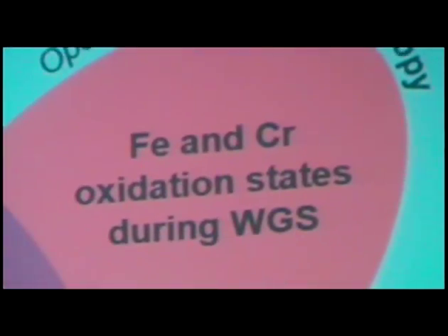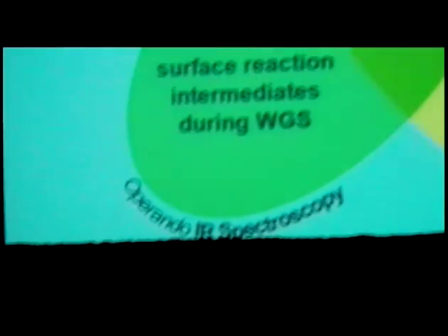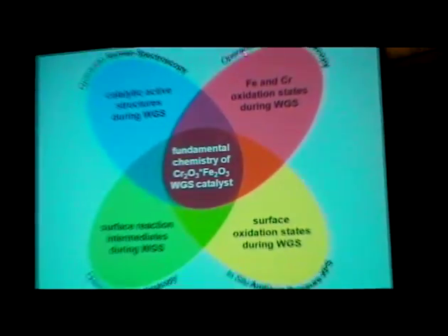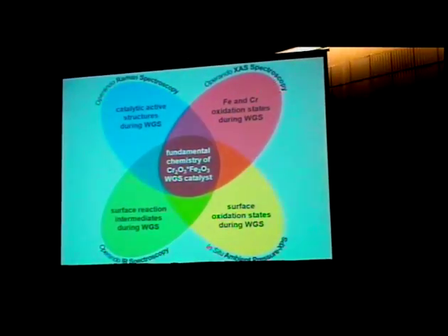So this is the strategy that we took to learn about the catalytic active structures during the water gas shift. We performed so-called operando Raman spectroscopy, hooking the Raman spectrometer in the reactor to a mass spec online. We also performed operando X-ray absorption spectroscopy with a mass spec online at the same time, to get information about the iron and chromium structures and oxidation states, to get at the surface information, the oxidation states of the chromium and iron.